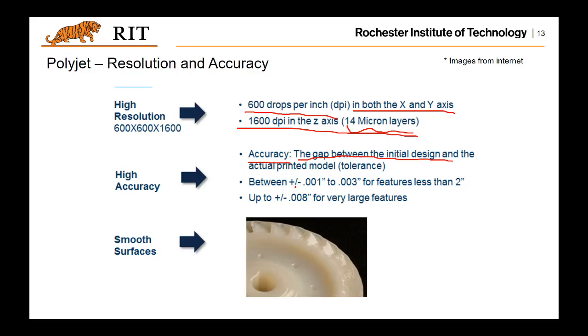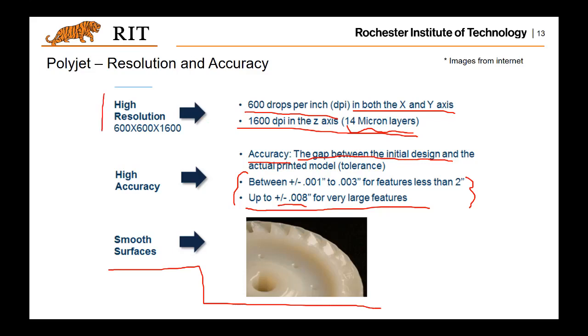That's possible. Basically, its tolerance is between positive and negative 0.001 inch to 0.003 inch for a feature less than 2 inch. If you're talking about a very large feature, then the tolerance will be positive and negative 0.008 inch. But still, it's relatively smaller than fused deposition modeling. And you will have really smooth surfaces if using the very high resolution of the prints.